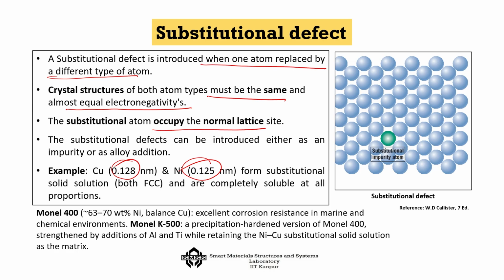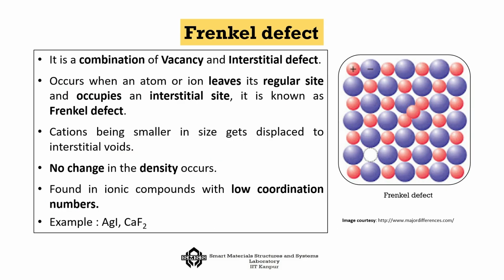So, you can essentially say that they can form a solid solution, and we take good advantage of it. Monel 400 has about 70% nickel and the balance 30% copper, and this is excellent in terms of corrosion resistance in marine and chemical environments. Sometimes we also mix it with aluminum and titanium, and then we get a new material called Monel K500, which is hardened also. This is called precipitation hardening. So, this is a substitutional defect, which sometimes has a very positive effect on a system.